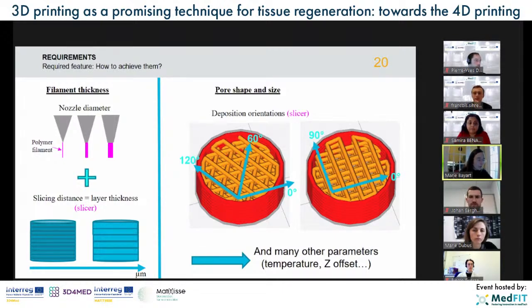And also we have to keep in mind to choose the good slicing distance. That's also in the slicer software of the machine, to choose the layer thickness. Depending on the nozzle we chose, we will choose a different layer thickness. Also for the pore and shape size, we can choose different deposition orientation, also in the slicer. So here you've got 2 examples. You've got 0, 60, and 120 degrees, and 0 and 90. You see that these different deposition orientations will give different pore shapes, triangular or square, and also different sizes. So this is to keep in mind when we design a scaffold. And there are many other parameters such as temperature and the Z offset, but I will talk about them later.